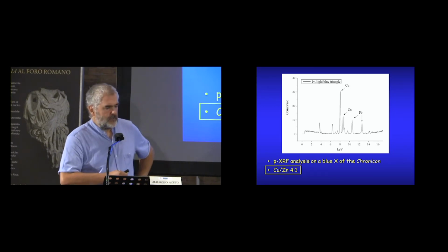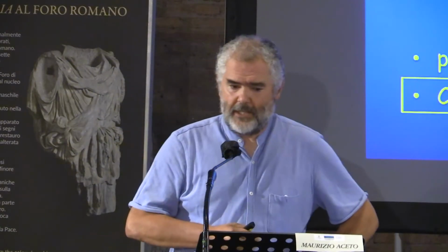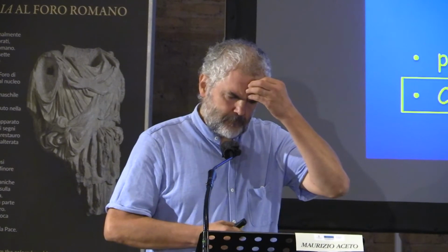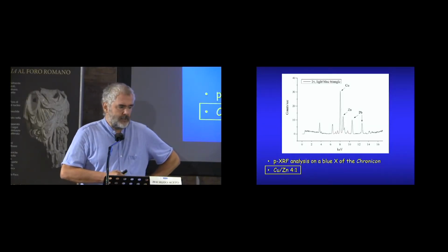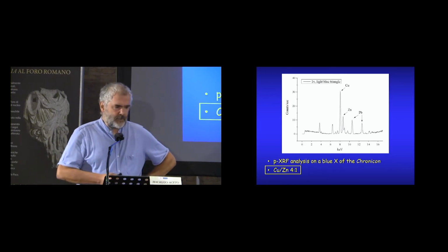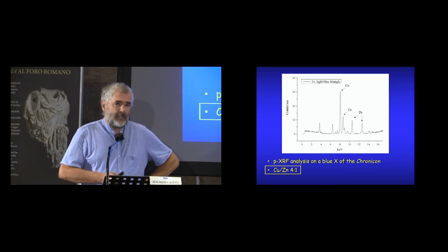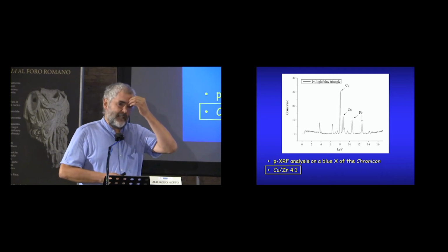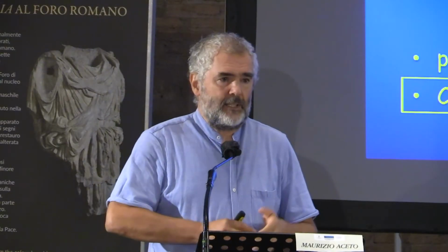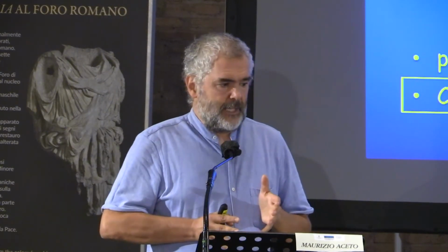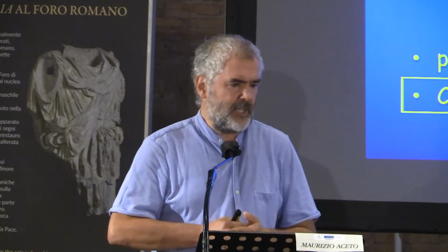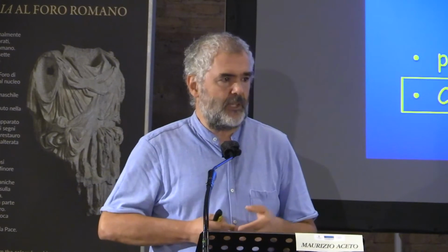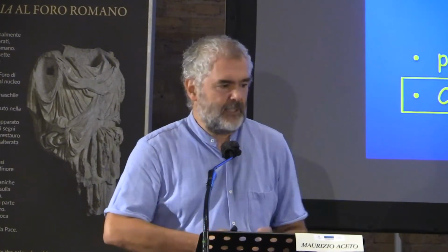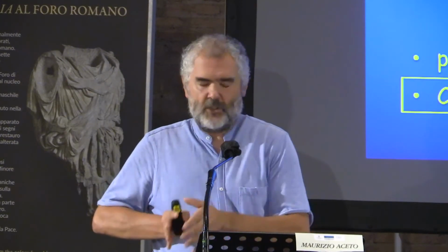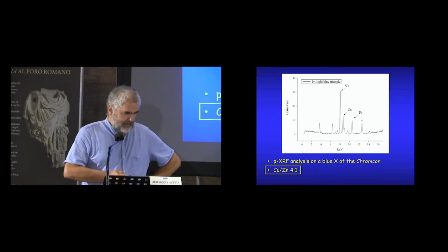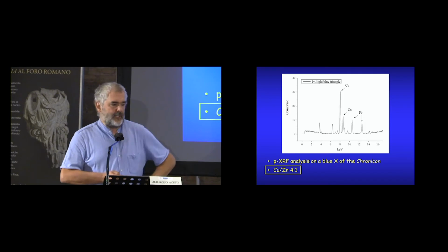I was talking with Marco Nicola before. He suggested me another case, a fourth case, coming from a study of a church in Hierapolis in Turkey. It was published a few years ago by Vettori and Bracci, and they had the same result. I mean, they published an XRF spectrum where there is apparently copper and zinc, and it seems like the same ratio. I'm saying it seems like because they didn't yield a quantitative result. We don't know why. We discussed this, but the authors just say that there is Egyptian blue and nothing about the composition. But we can say there are 4 cases.